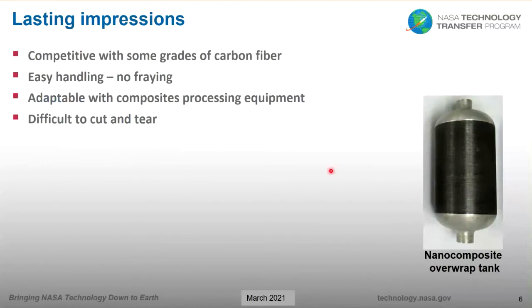So there are many grades of carbon fiber, such as high modulus carbon fiber or high tensile strength carbon fiber. But we do know that the nanotube yarn that we worked with was competitive with some grades of carbon fiber. We noticed that the nanotube material was very easy to handle and that we did not observe any fraying, unlike when working with other bundles of fibers.